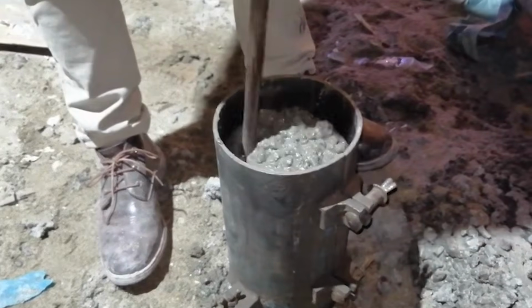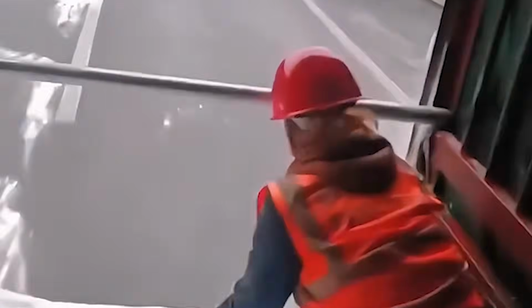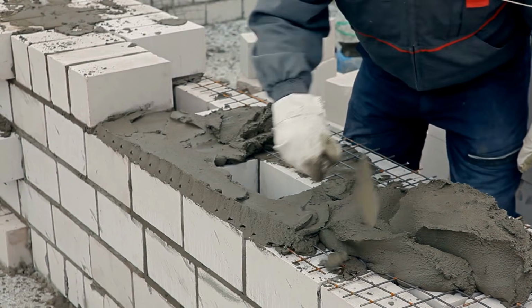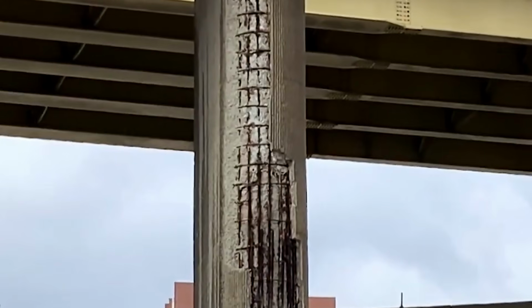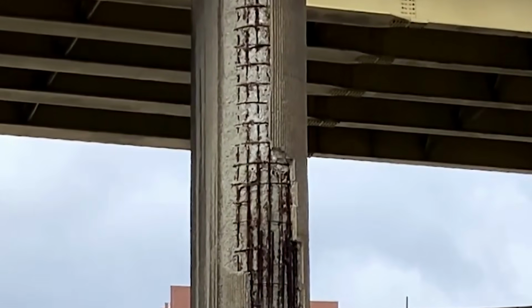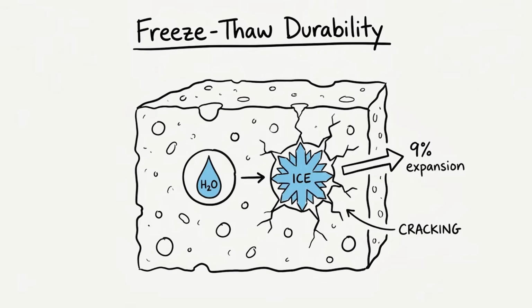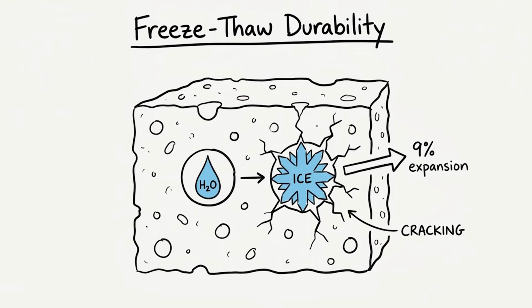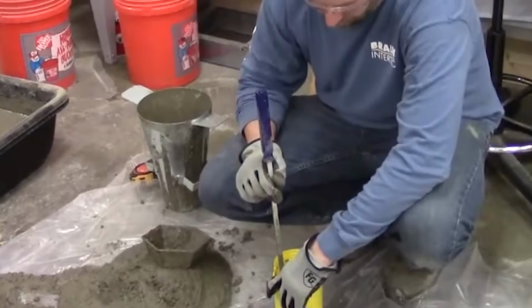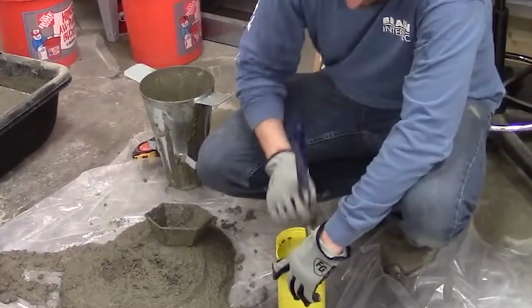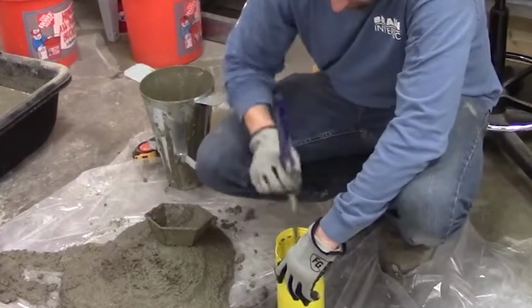Here is why squeezing out those voids matters so much. Those tiny gaps are where nearly every concrete failure begins. Cracks start at voids. Water seeps in through voids. Road salt and the chemicals in seawater travel through voids to reach the steel reinforcement buried inside, where they trigger corrosion that eats a structure apart from within. Freeze and thaw damage happens when water trapped in a void turns to ice and expands. Shrink the voids and you knock out most of concrete's long-term weaknesses in a single move.